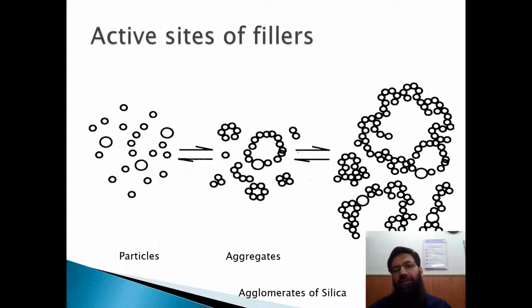So the tendency of making aggregates and agglomerates in the silica would be more as compared to the carbon black, because silica has more active sites and more interacting sites as compared to the carbon black. But it doesn't mean that if the silica has aggregates and agglomerates, it cannot be dispersed.